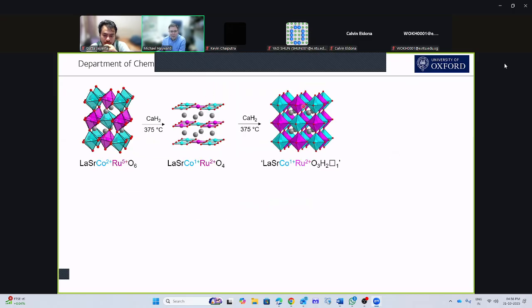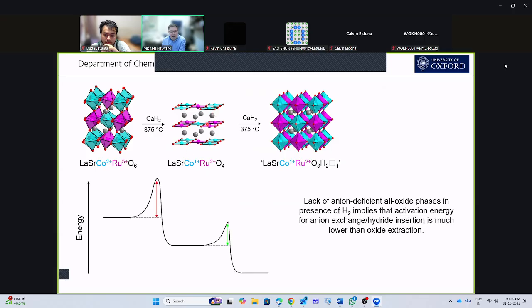The implication in this sequence, because we don't see this intermediate if we have hydrogen present, is that this first barrier is larger than the second. So if I add enough energy to get over this first barrier, I can't stabilize this material here because I immediately go over the second one and make the oxyhydride. So we can understand why we get oxygen deficient intermediates or not by the relative size of these activation barriers.